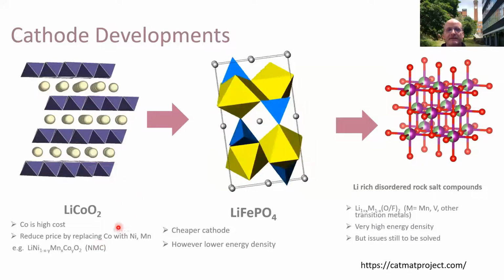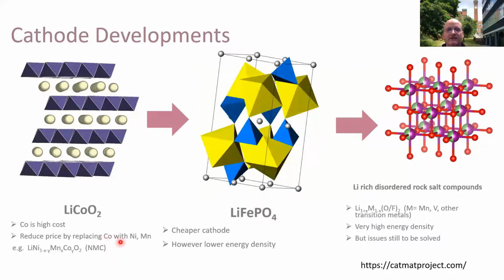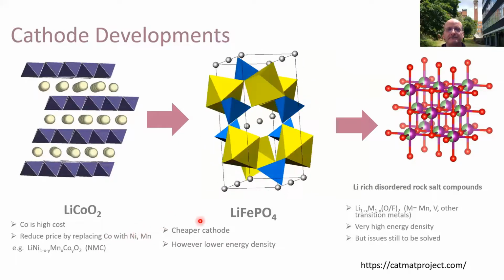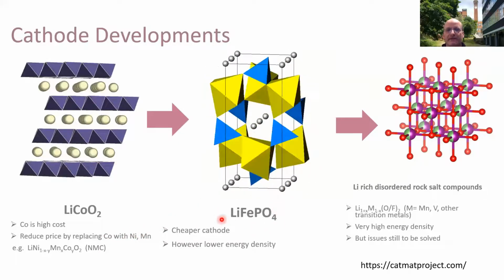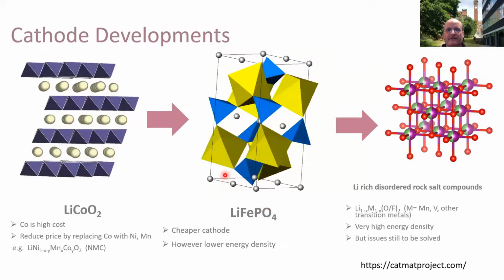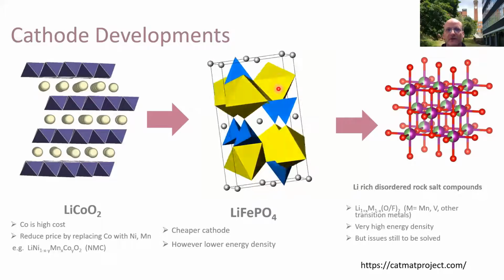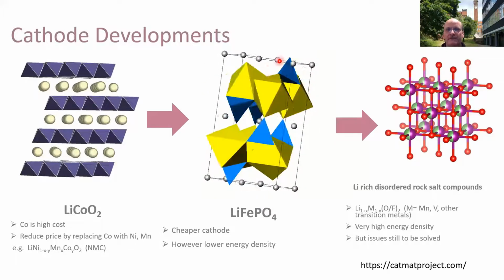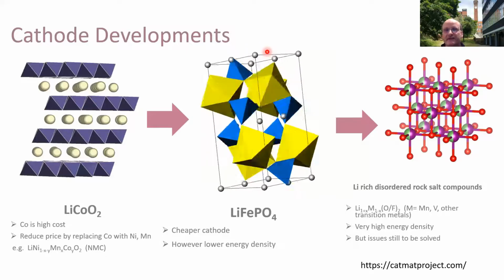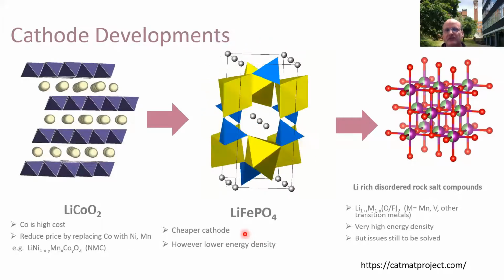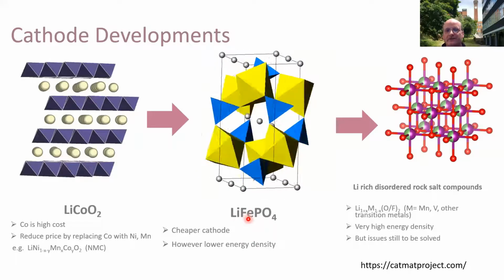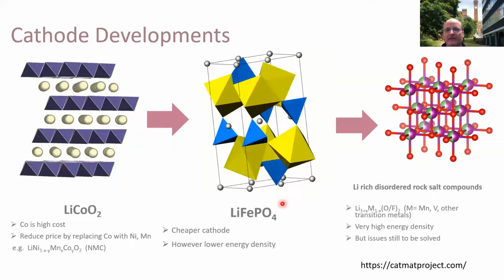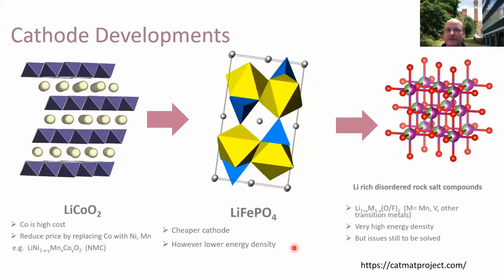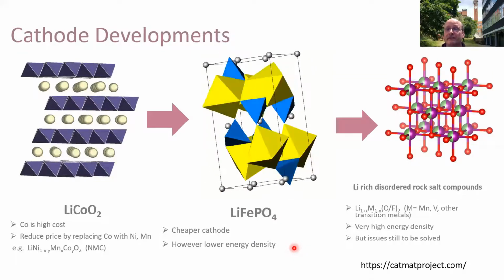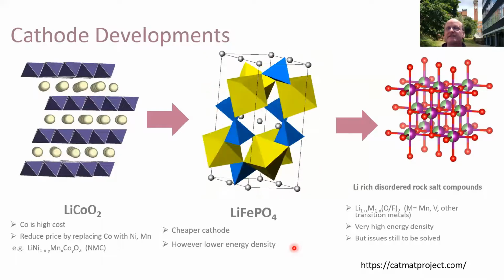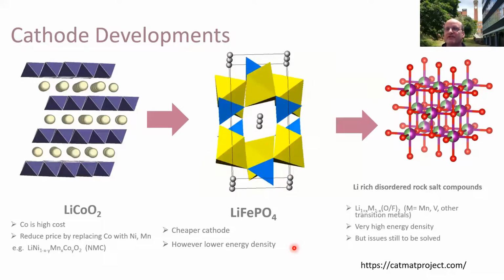Now, because of the cost and sourcing issues of cobalt, and also the growing cost of nickel, there's this lithium iron phosphate material, which is no longer layered. It has iron octahedra separated by phosphate groups, and the gray spheres are the lithiums. This is a much cheaper cathode because it's got cheaper materials, iron, but as I said before, it's heavier, and so it's got lower energy storage. So companies like Tesla are looking at these for models where you're less concerned about range, but what you want is a cheaper battery.